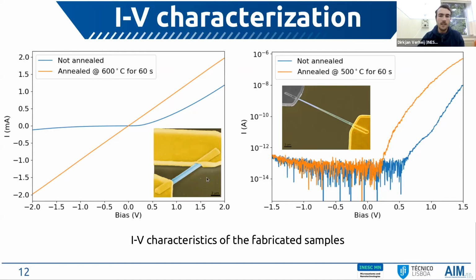But after annealing at 600 degrees Celsius for 60 seconds, we obtain a nicely linear IV curve, meaning that the contacts have become ohmic. So the electrical property of the PN junction diode is obviously completely different due to the rectifying nature of the device. However, we still see an improved electrical characteristic after annealing.